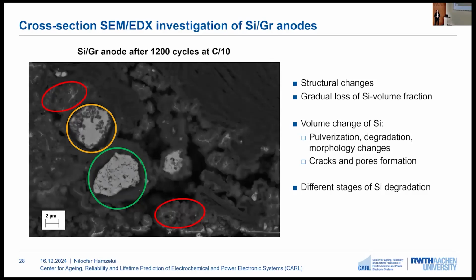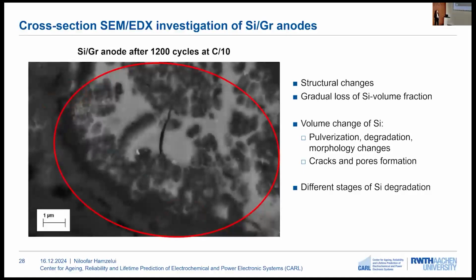We can see complete degradation of the silicon particles. So based on this SEM image, we can say that one reason that we are not reaching the theoretical capacity of our electrode could be that some of the particles, for example this green particle, are not contributing to the lithiation and delithiation as much as the other particles which are marked in orange and in red. Here is a closer view of how the particle looks after electrochemical cycling. We can see a clearly visible crack here and also the degradation and the loss of volume fraction of silicon particles.